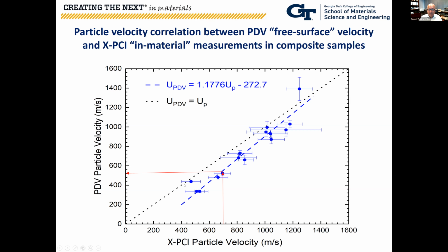Otherwise, both particle velocity trends give us the same linear relationship, meaning the shock and particle velocity measurement we're making with XPCI is very much correct and in line with what you observe with the PDV. So it gives us backing support that XPCI measurements are fairly reliable.